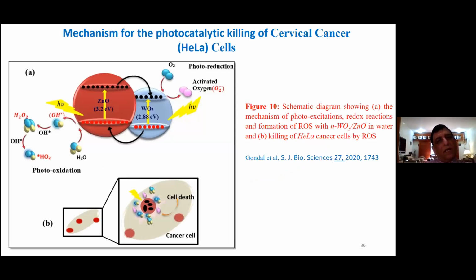nanocomposite. Again, in the excitation process we have a heterojunction between these two catalysts, and we can shine, first of all, for example, 2.88 electron volt on this, and then we tunnel the electron to this. So we can shine the light either way. We can use either laser light or a broad spectral lamp, and we can excite this and generate OH radicals, and these OH radicals then go and target the HeLa cancer cells, and the HeLa cancer cells are killed by this radical reaction.